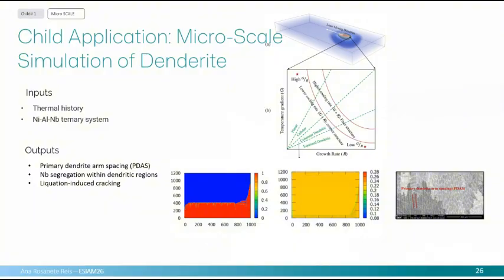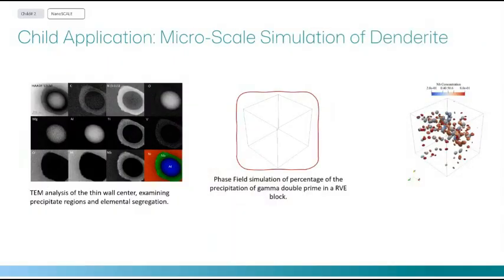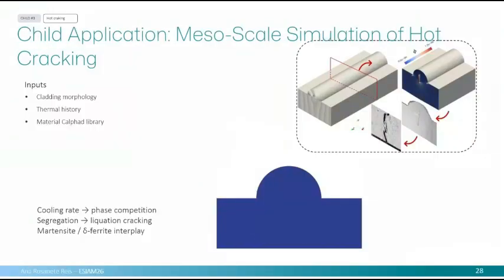But then we found out that Inconel is a very complex material, and it segregates some phases. So we need to go one scale ahead, and we go to the nanoscale, I think, to do the precipitation modeling. This is quite interesting because we could also make some validation. And this is important because then you can understand where the component has the ability to form cracks. And then you go back to macro scale, and we have everything to try to model the crack behavior.